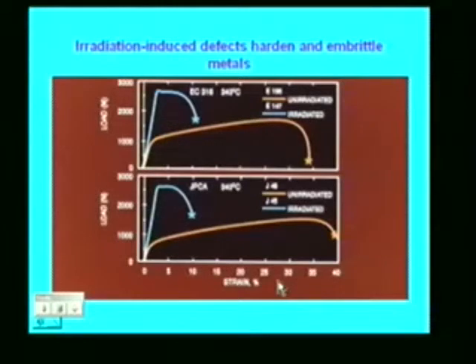Well, I also said that irradiation-induced defects that we talk about harden and embrittle metals, and I've illustrated that by some stress-strain curves, again from stainless steel. And you notice here that in the unirradiated case, we have about 30 to 40% elongation. After irradiation, it's only about a quarter of that, and it has doubled in strength. Well, that's nice that it doubled in strength, but the ductility is something that's going to hurt us.